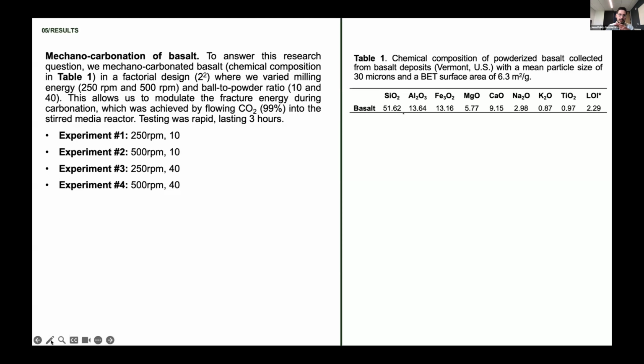Now we're going to test the 4 conditions where we're varying 2 different variables in this mechanical carbonation process. The first one is the milling energy, which is in revolutions per minute or RPM. We have 2 conditions there: 250 RPM, which turns out to be a low milling energy, and our higher milling energy at 500 revolutions per minute. We're also varying how much ball media for grinding we have in comparison to the basalt powder. So we have 2 different ball to powder ratios, 10 and 40. Testing for mechanical carbonation in this particular study only lasted 3 hours, so all the results that we're going to show you are for 3 hours of mechanical carbonation.